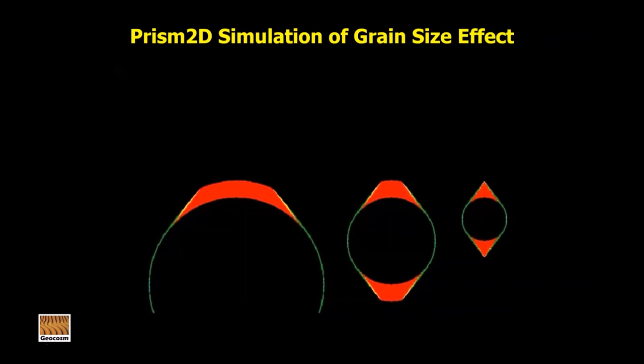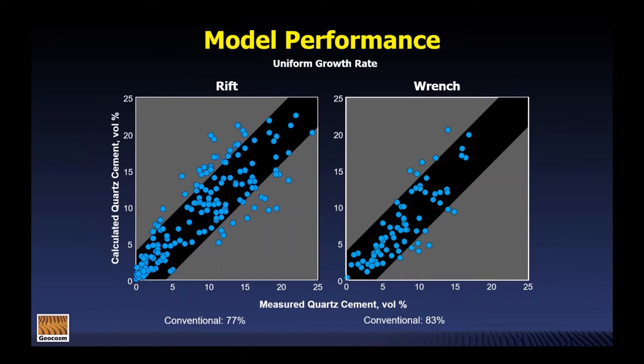So now, after breaking down the model performance, seeing where there's a systematic error, and doing some experiments to understand the cause of that error, we now have some new understanding. And the question is whether, by having that new understanding, we can improve the predictive accuracy of our models. So just to remind you where we were, this is what the results look like when we assume that the rate of growth per unit surface area is independent of the size of the grains that the quartz is growing on. It's uniform over all the grains.